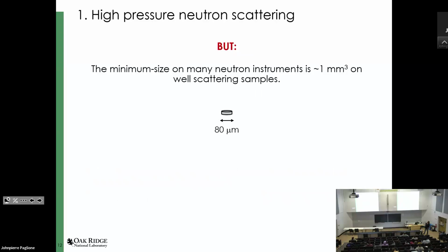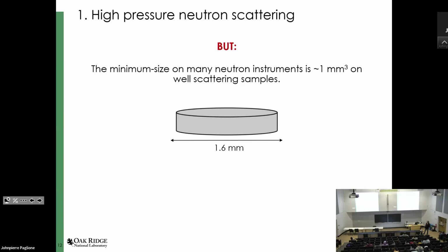So the minimum size on most instruments would be 1 cubic millimeter, and most people will already call me crazy by just using such a small number. I mean, neutron beams are usually measured in inches. That's the size of the beam they will give you. So such a small sample volume doesn't typically work. So to get to a 1 cubic millimeter sample volume, you need to scale up your sample.